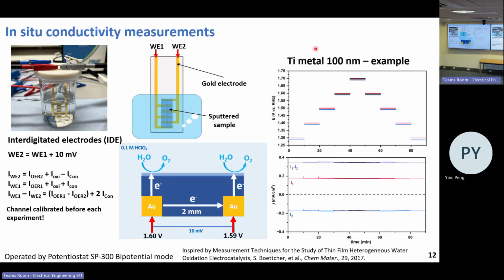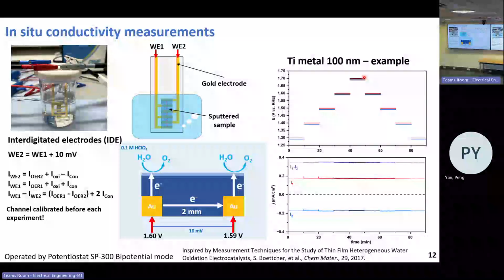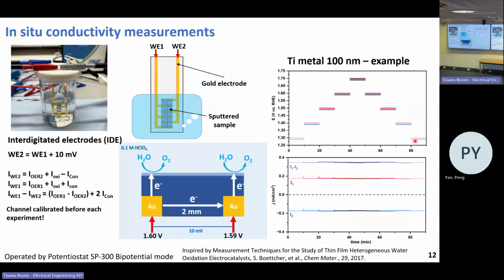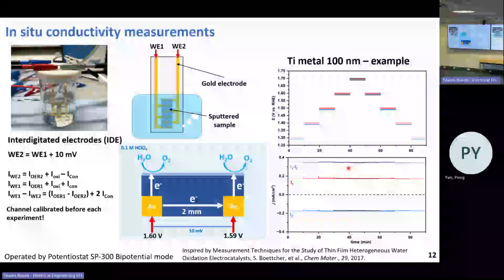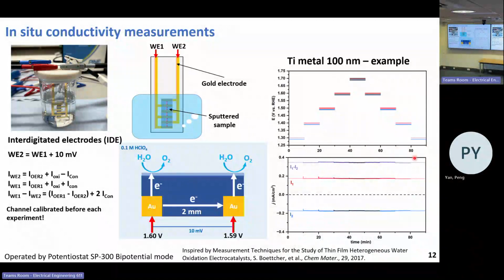Here's an example of 100 nanometers of titanium metal. So we can scan from 1.3 to 1.7 versus RHE and went back to 1.3. This symmetrical current means there's no Faraday reaction happening, and the difference of this current is proportional to the conductivity of the sample, according to Ohm's law.